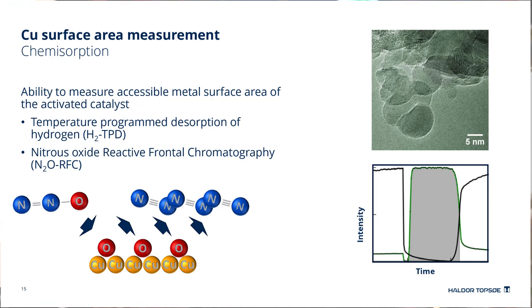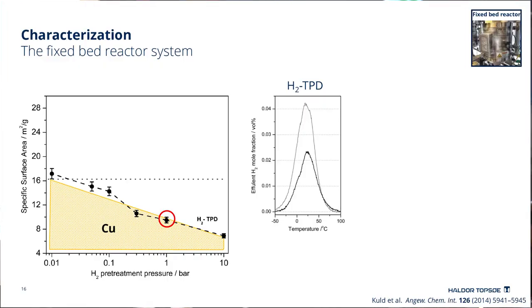So here is a profile. Initially, you have nitrous oxide here. Here the reactor is bypassed in this part. You have nitrous oxide and nitrogen. And then as soon as you open into your reactor, you have nitrogen coming and nitrous oxide disappearing. And at some point, when you have no more area left to do this reaction, you have a nitrous oxide breakthrough here. So based on the amount of consumed nitrous oxide, you can calculate the amount of copper in the catalyst surface. So we have two individual independent ways of characterizing the surface.